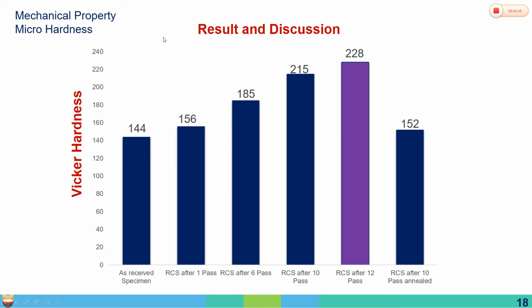Finally, we quantified the microhardness results, which say that microhardness increased up to 228 after 12 passes. Surprisingly, after annealing it is obviously reduced. Further research is going on after 24 passes. Definitely it will increase the strength of the material. About 228 hardness was achieved.